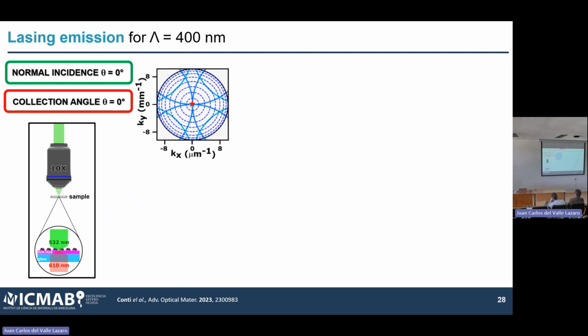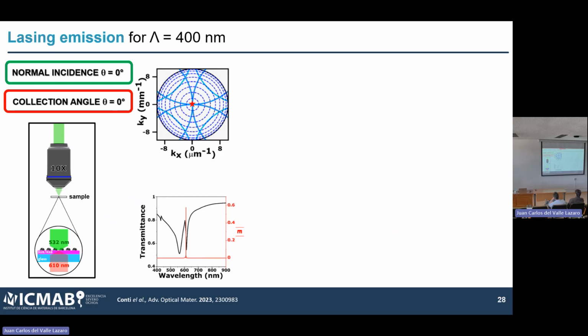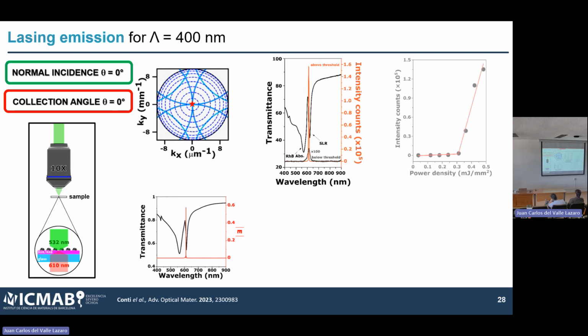and the way you look at this graph, this is a K-plot, this means normal incidence or normal emission in this case. So the idea was we pump the system from the top, and then there should be this interaction, and the rhodamine B should start to emit normally to the surface. So this is the theoretical prediction. And this is the experiment.